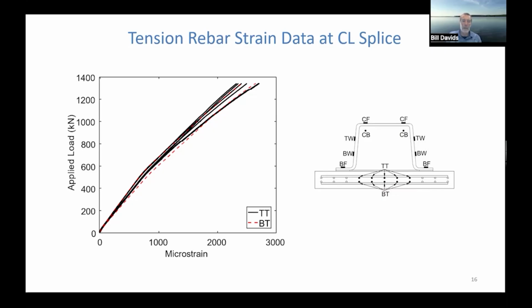Okay, if the steel had yielded, you would see a very large increase in strain with small increase in applied load. That's what happens with reinforced concrete sections once the steel starts to yield. And this is right at the centerline splice where it's just reinforced concrete. We don't see that. 2,700 microstrains also corresponds to a stress of just under 80 KSI.